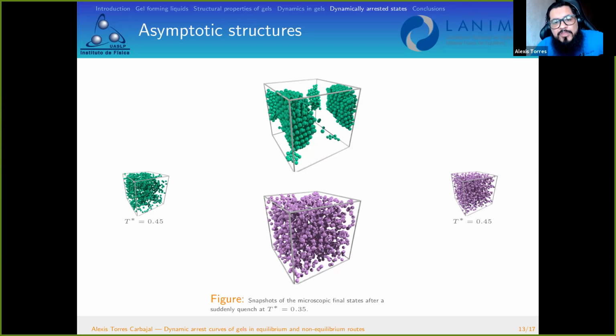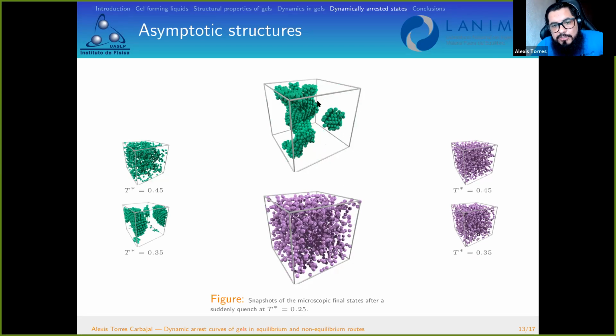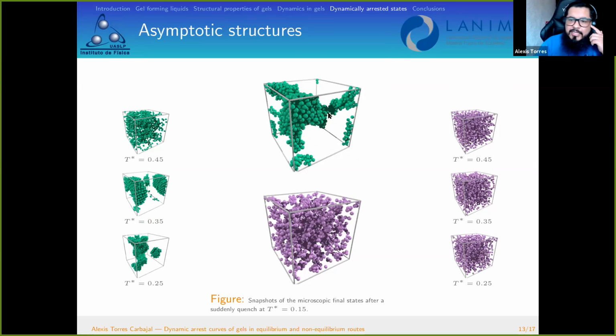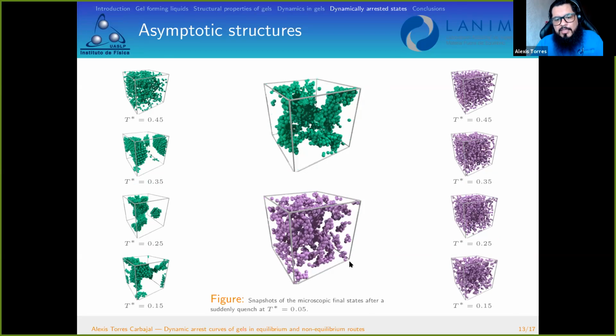If we further decrease the temperature, we observe now that the Lennard-Jones tends to form this kind of structure. Meanwhile, the Lennard-Jones with Yukawa remains in a fluid state. If we decrease the temperature further, this structure in the Lennard-Jones fluid changes its shape according to this snapshot. But here in the Lennard-Jones with Yukawa tail, we cannot see very clearly if some kind of structure is formed.